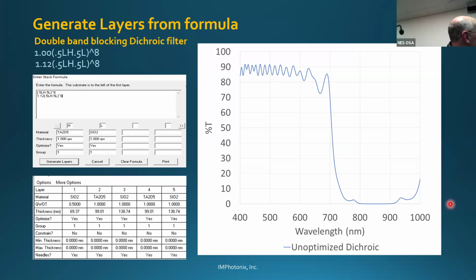We take the formula, and this is TF Calc. TF Calc came out in the 80s, and it's one of the more popular thin film coating software packages. The nice thing about it is you can plug the formula right into your formula equation, specify your material, what you want for high and low index, and have it generate the layers. In this case, this is a 33-layer dichroic filter of alternating high and low index materials, SiO2 and tantalum. Each layer of tantalum is the same, except that we're doing a quarter wave here, an eighth wave, and then this is a quarter wave. And they're all the same.